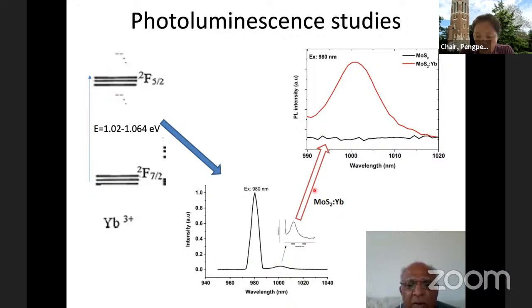peak from ytterbium. When you look at it in detail, you don't see any ytterbium peak in the undoped film, whereas in the doped film, we see ytterbium emission. This emission is much, much narrower than what we see in glass and bulk materials. So this room temperature PL data is quite important. Further work is required to characterize the lifetime of ytterbium ions in thin films.